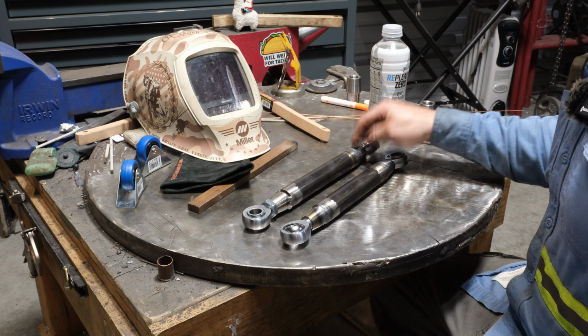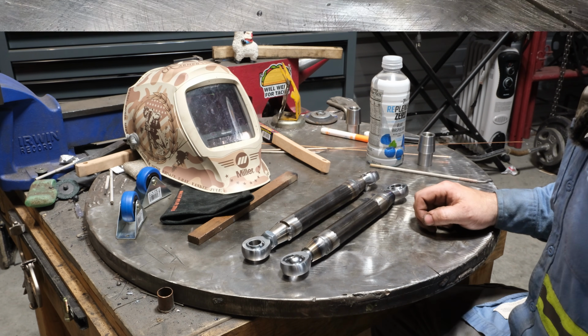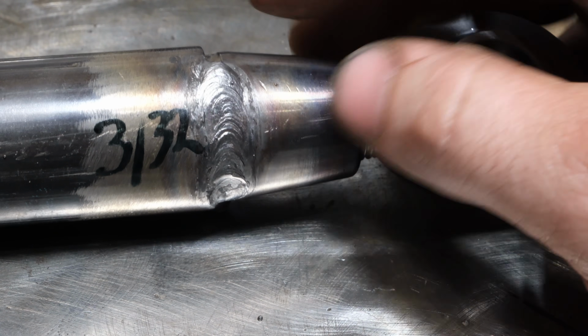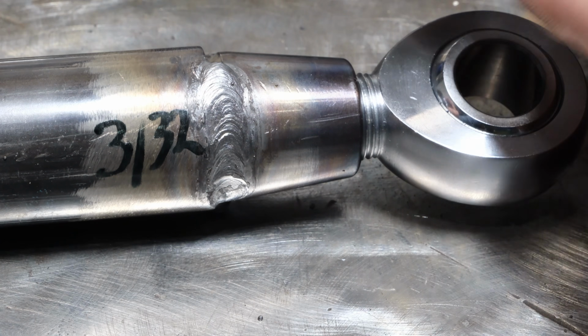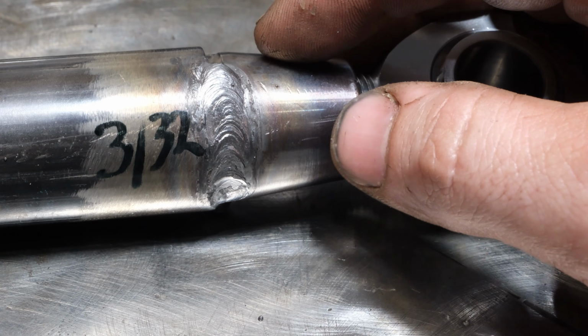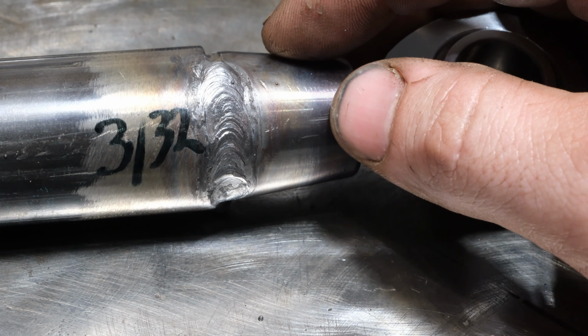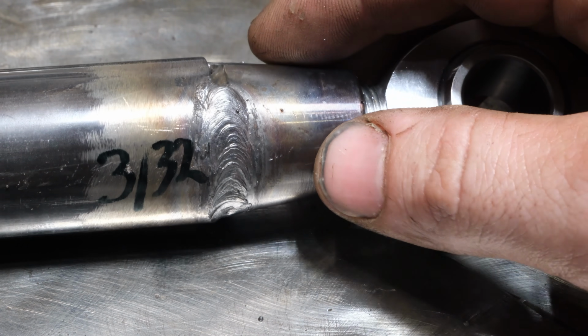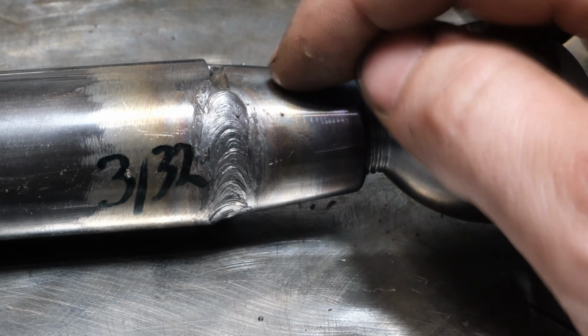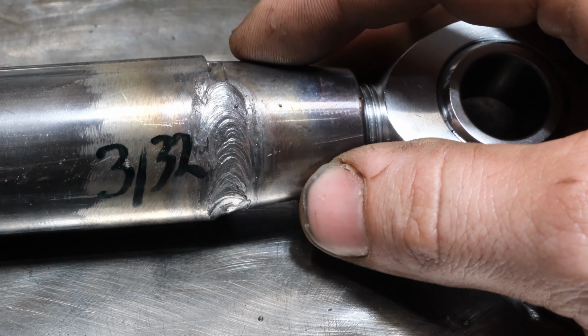Well, let's start out by looking at an up close of the stick weld. So the first weld I did was 3/32 rods, 7018 at about 100 amps, which I would say is ideal for this 3/16 tubing and this particular rod end insert.